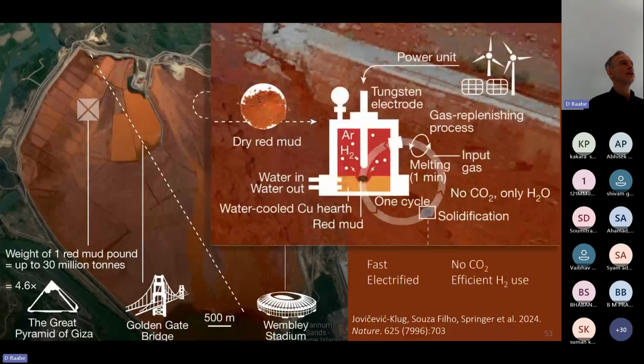And we use this dried red mud, like we use iron oxides, as feedstock for plasma-based, hydrogen-containing plasma-based smelting reduction processes. And that runs in a very similar way, as I've shown before, for the case of iron, where we use hematite, but now with this much higher contaminated oxide material, which contains, as you know, iron oxide, some rest of aluminum oxide, titanium oxide, silicon oxide, and even rare earth metals and so on. So it contains all kinds of materials.